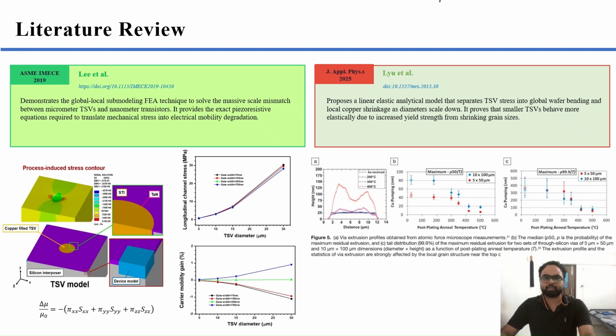The last set of graphs shows a fascinating and very practical problem. Copper physically extrudes or pumps out of the top of the TSV. The graph shows the height profile measured by atomic force microscopy. The pink curve after the 400 degree cycling shows copper sticking out up to 175 nanometers above the silicon surface. Graphs B and C compare two TSV sizes, 5 by 50 micrometer and 10 by 100 micrometer, and show how extrusion occurs at different annealing temperatures.